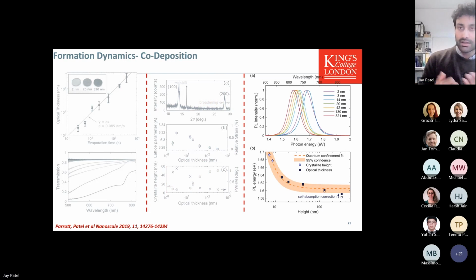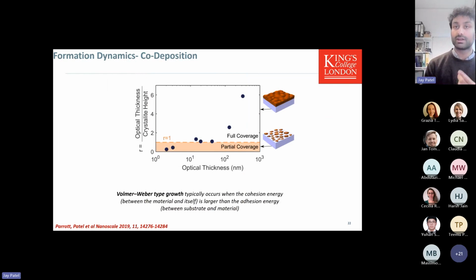To understand what's happening at these very small thicknesses, we did a photoluminescence experiment, where we shine light on the material and see what light is emitted. We found that at the very, very thin films that we grew, the photoluminescence shifted. This means there's a quantum confinement effect. Because the crystallite sizes are so small, the band gap has increased, and you see a blue shift in photoluminescence. Using a combination of all these results, we were able to build a picture of how the crystal grows. Initially you get these island crystals where you can get confinement of the light, and you get a change in band gap.